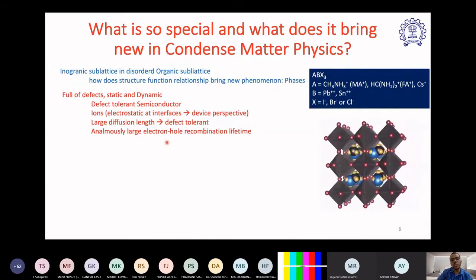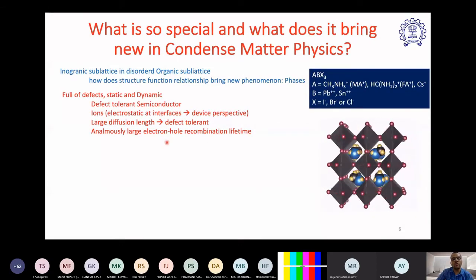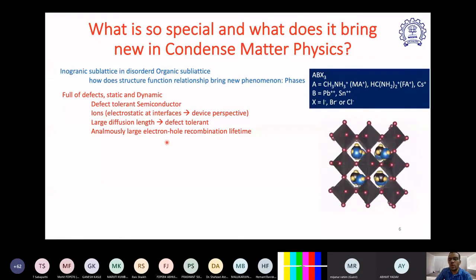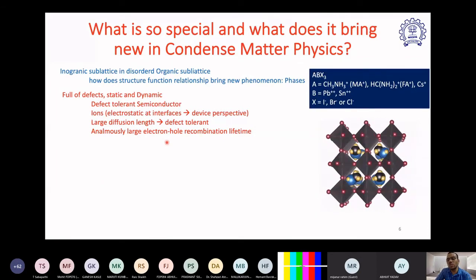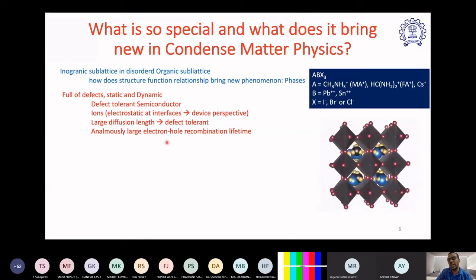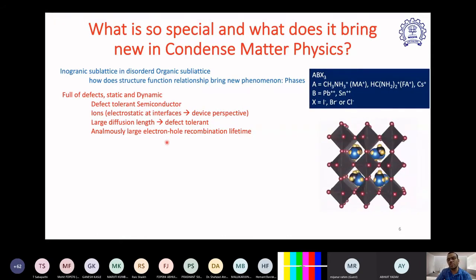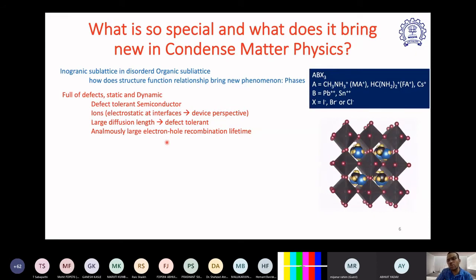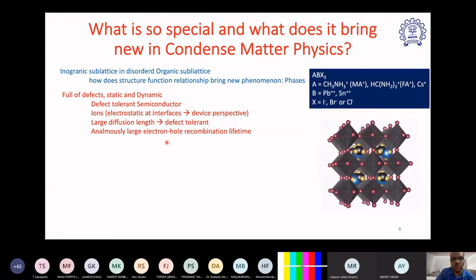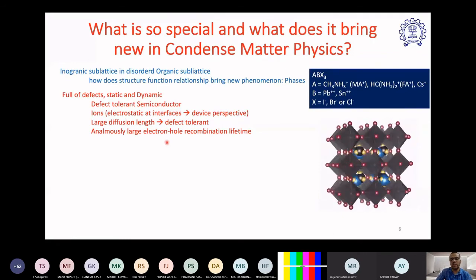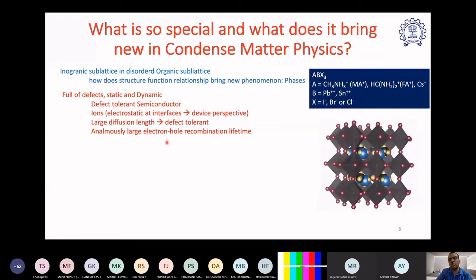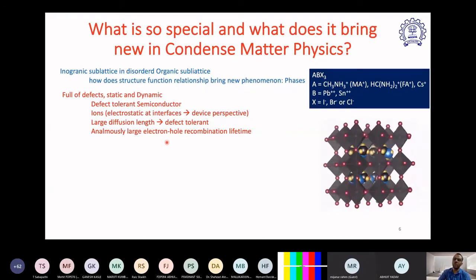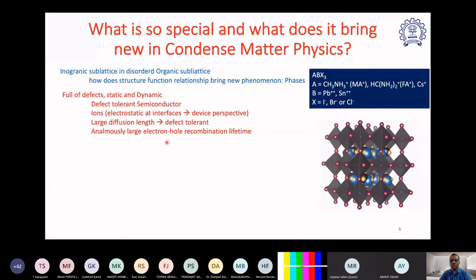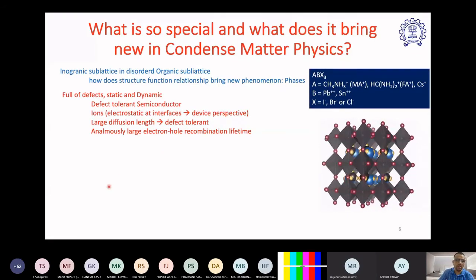And it also shows anomalously large PL lifetime. Why do I say anomalously? Because you have a very high PL lifetime, but the quantum efficiency of these solar cell materials is very low compared to what we see in gallium arsenide. Gallium arsenide internal quantum efficiencies are close to 100%, 99.9%. If you have a gallium arsenide film made by MBE, it will have a PLQY close to 100%. But these materials give a PLQY of only 15-20%. So low PLQY but very high PL lifetime is a bit of an anomalous character observed in these semiconductors.